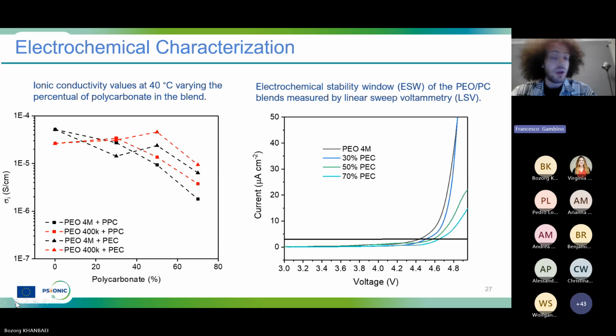Together with the ionic conductivity, we also evaluated the electrochemical stability window. Since polyethylene oxide is known to be a not very stable compound that degrades around 3.9 volts, while polycarbonates are known material to be more stable. In fact, we observed an effect by the addition of these polycarbonates, and using a threshold of 3 microampere per square centimeter, we compared the current developed by increasing the voltage of this material. We can see that the PEO starts to degrade in fact at around 4.3 volts, while when there is an addition of the polycarbonates, there is a beneficial effect, and the electrochemical stability window shifts to higher voltage as the amount of polycarbonate is increased. Next slide, please.